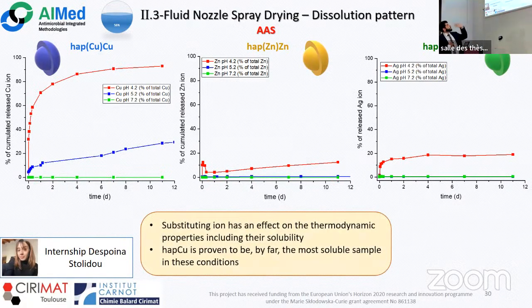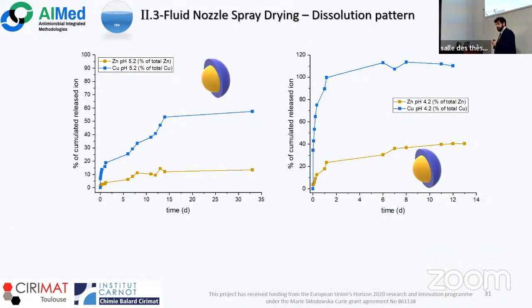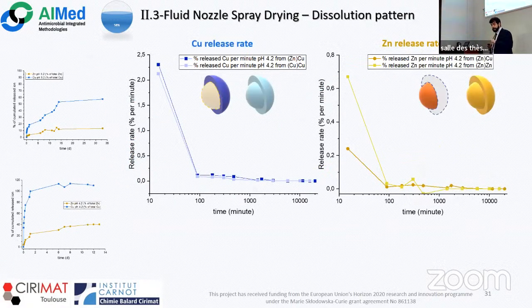At first, looking at the dissolution patterns of the monosubstituted particles, it pops out that the substituting ion has an effect on the thermodynamics of the particles, and of course related to that, on the solubility. And we can observe that in the time range that we studied in these experiments, only the copper apatite was almost completely dissolved. The zinc and the silver apatite were clearly more stable. When we started to study the core shell zinc copper particles, we observed, of course, the same patterns. But we wanted to deepen the study of these dissolution patterns, so we calculated the release rate that we had in these systems.